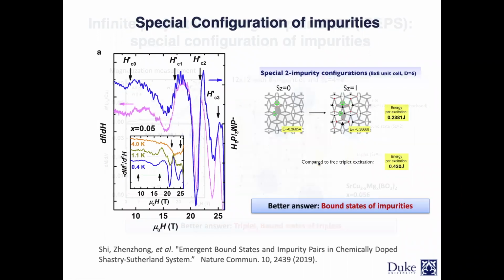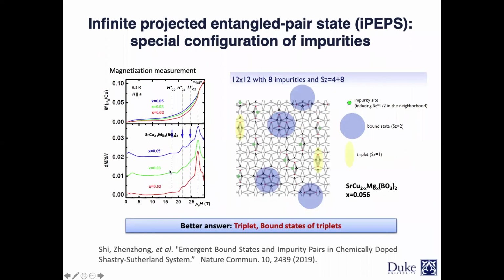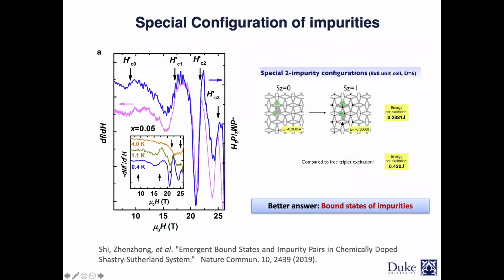The impurities themselves can also bind together, which is very important. Creating a bound state of particles, given that the concentration was really low, was quite surprising to us. But when the theorists modeled it, they said the energy is in accordance with what you are seeing for these wiggles. Through this, we were able to discover these new states in impurity-doped strontium copper borate.